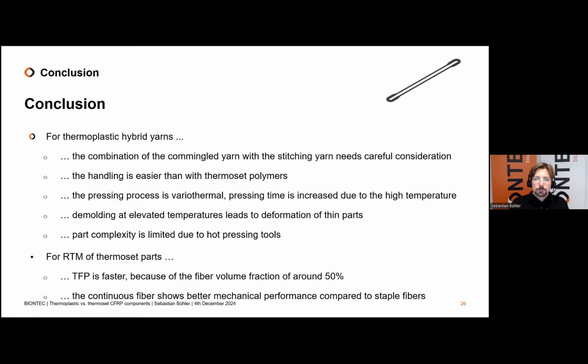The handling is easier than with the thermoset polymers, because we only have the press process. We do not have to use the injection unit. We have no degassing of the material, so we have a closed process, and it's a very clean process. Of course, the pressing process we investigated and saw the best chances to gain a very nice part is the variothermal process, and the pressing time is increased due to the high temperature for the thermoplastic matrix.